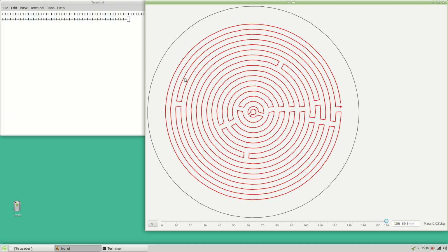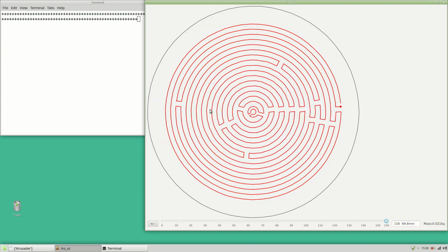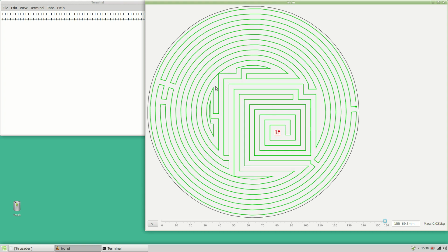The very last layer is the collector. It's a thin layer, actually it's an auxiliary layer thickness, which in this case is 0.5 millimeters. The purpose of the collector is to collect the molten infill metal. If your runner would be here and you place your infill metal, it might not touch it, or it might. If you have a flat pancake and it touches the runner,